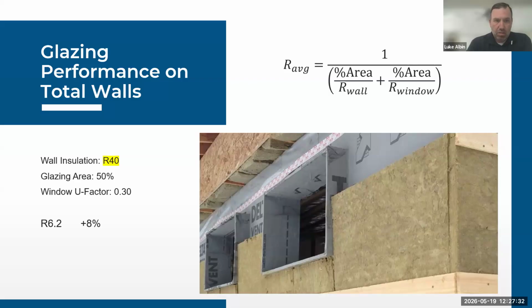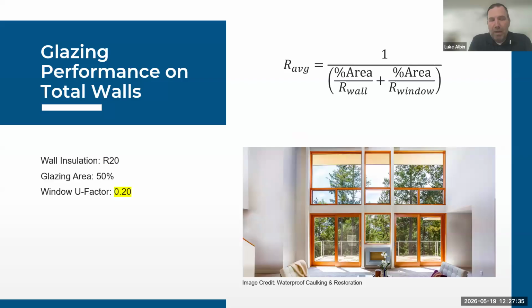So instead, we're going to put a better window in. So wall insulation R20, same glazing area. But instead of the R3.3, we're going to use an R5 window. Now we've gone from 5.7 to an R8, so a 40% increase. So this is just to show how significant, and I realize that 50% glazing area is a pretty substantial percentage, but you can see that there's really a much more dramatic effect simply by using a better window than having to build out the wall insulation itself.